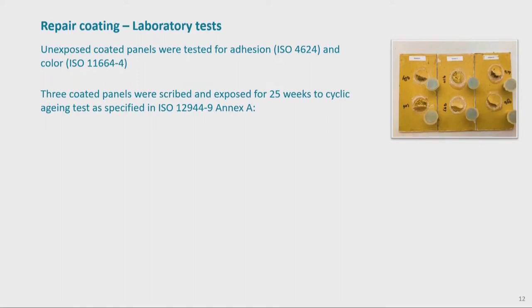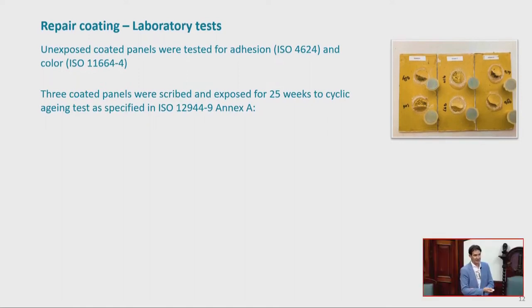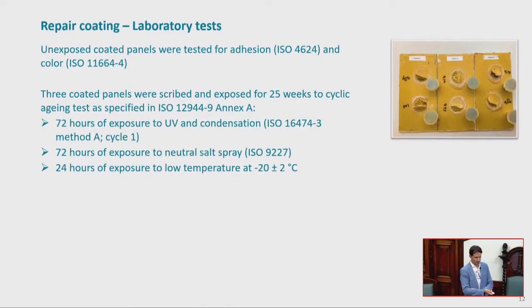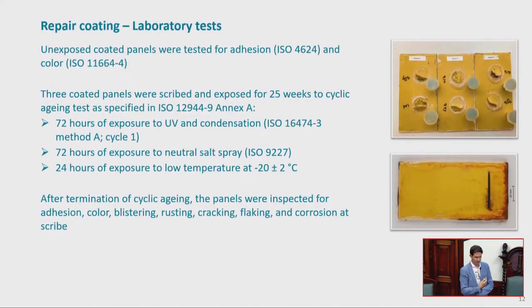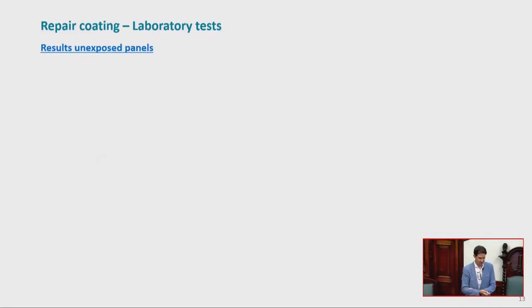So how is the pull-off test and so on? Again, it's not a coating. You're not going to get much force needed to get cohesive separation because the material stays in its tacky form over time. So when you get any value, it's a cohesive fracture value rather than an adhesive failure value. So these are the things you need to consider. But fine. So we go through, of course, all the exposure hours, etc., to do that and to bring it to a part, where we test that. And then, most importantly, corrosion and scribe, because corrosion and scribe is one of the things that many people are looking for. So here are the, am I at the tests? Yes. So here are the tests.